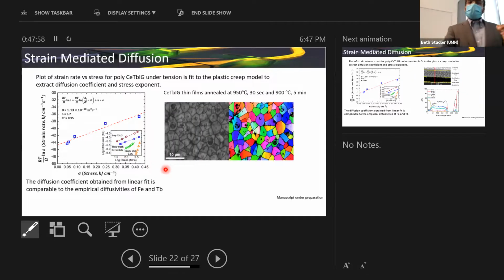Moving forward, we take those films and anneal them at the recipe mentioned in the previous slide, and we see this beautiful stained glass pattern, which indicates that it's perfectly polycrystalline.